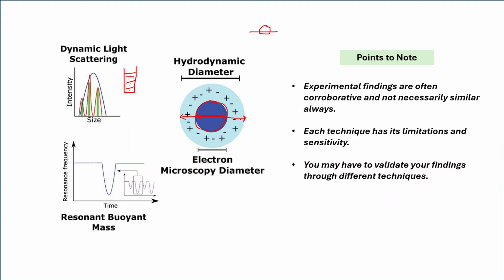So whenever there is a scientific publication, when you are publishing your data, it is always suggested not to rely on only one technique for your nanoparticle characterization, but to characterize your nanoparticles with different techniques so that you have a clear idea. Suppose you are getting 50 nanometer size based on your electron microscopy image, and based on your hydrodynamic diameter you're getting 70 nanometers. It's fine, and even if it's 100, there could be reasons.